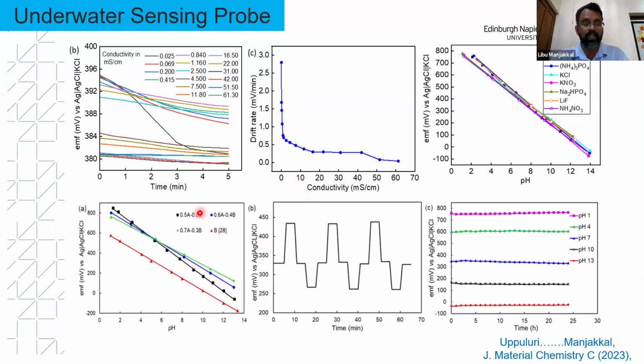One of the major achievements of this work is that we found a pure ruthenium based electrode has some issues, especially cost wise, so we mixed the composite with cobalt oxide. We compared the performance of different ruthenium oxide and cobalt oxide based sensing electrodes, and we monitored the sensor hysteresis, because when you measure pH sensing in different types of solution, pH up or pH down, hysteresis is one of the most important parameters. You can also see the sensor stability over different times, for example up to 25 hours, showing stable performance in solutions of different pH values.